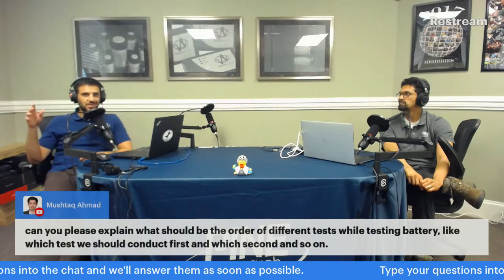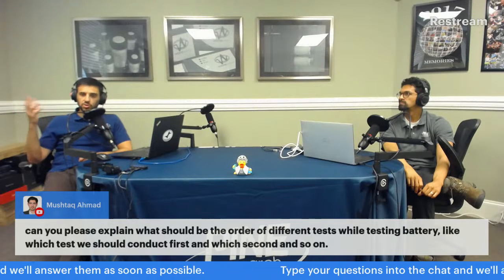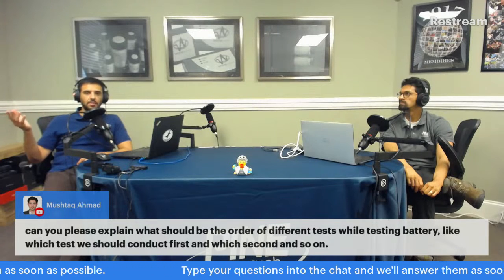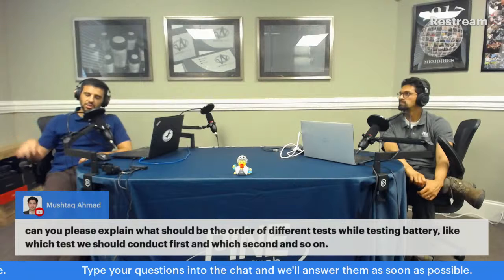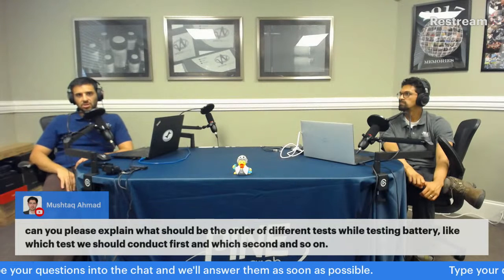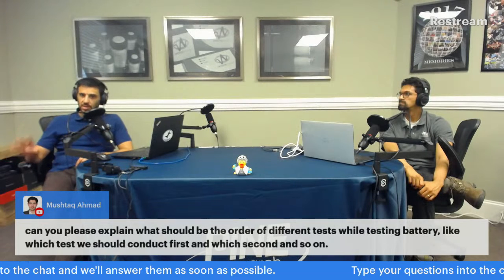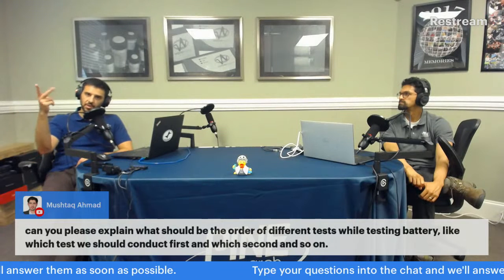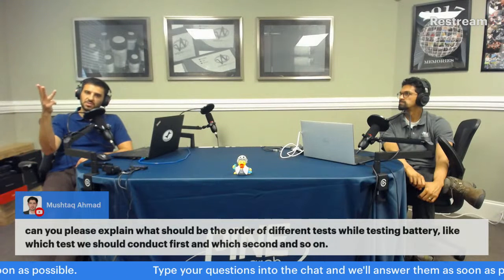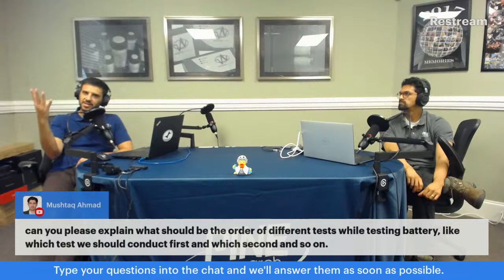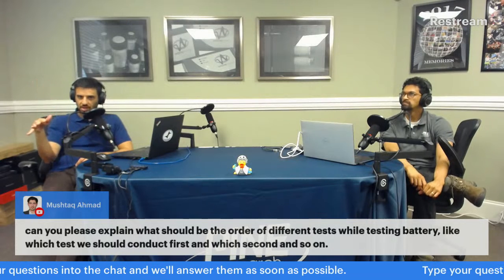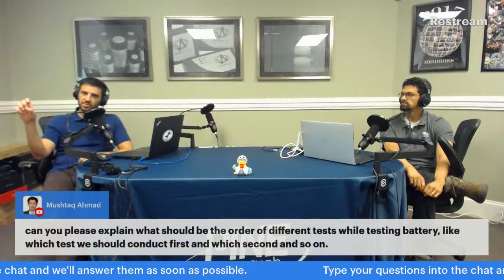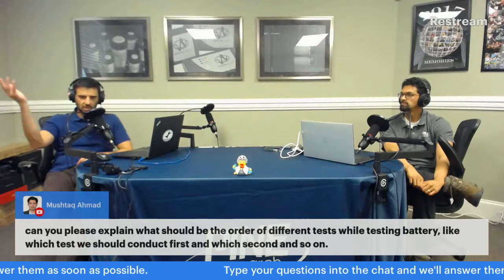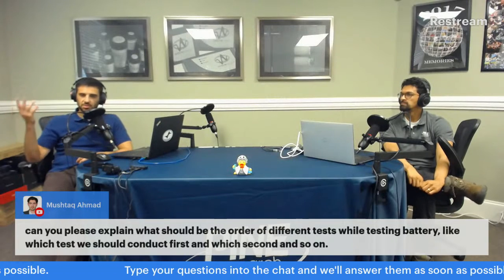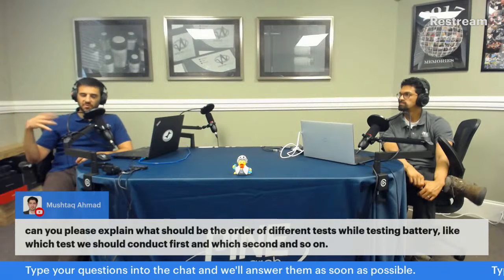And then you do OCP or OCV, rest at your 100% state of charge. And then you have a CC, constant current discharge, usually at the same current that you charged it at, but now you're doing a negative current, so you're discharging until you reach the bottom potential. So that's step 4: constant current up, constant voltage at the top, OCV at the top, constant current down. And then once you reach your lower voltage point, it's 0%, it's fully discharged. Another OCV step for good measure, just letting it rest before you do it all over again.